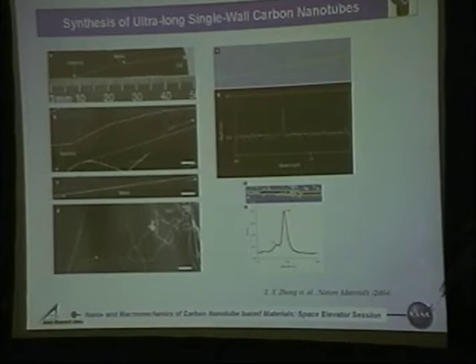But on the other side, these are very strong proofs. Those peaks you are seeing are the Raman spectra peaks, and that's the tube. That's a very strong signature, and they have taken that peak at different lengths in those tubes. So that's a very strong signature that this is indeed a single wall carbon nanotube. That's good progress: under certain conditions you cannot make a lot of them, but at least you can grow them long. So there was one thing.